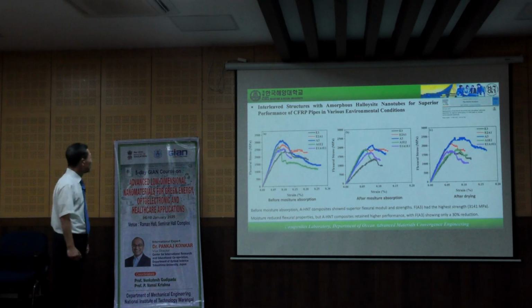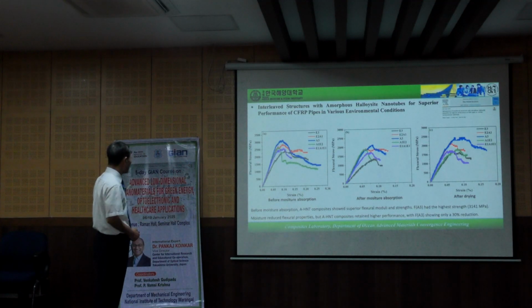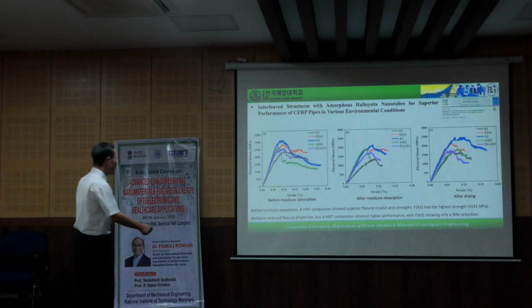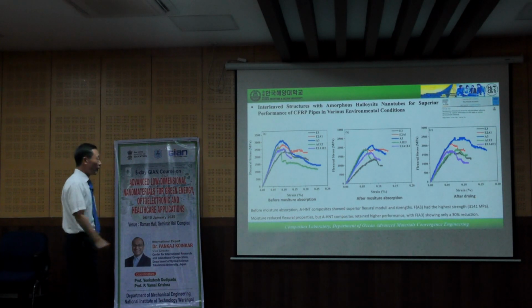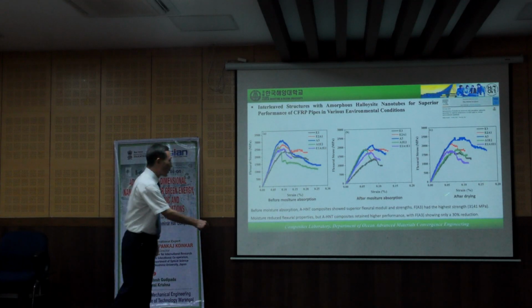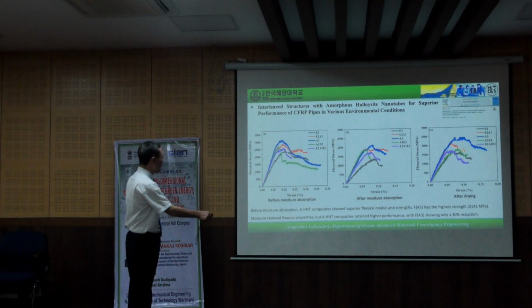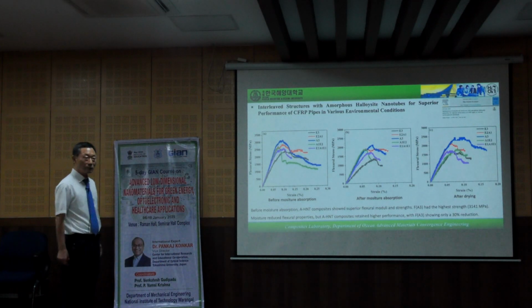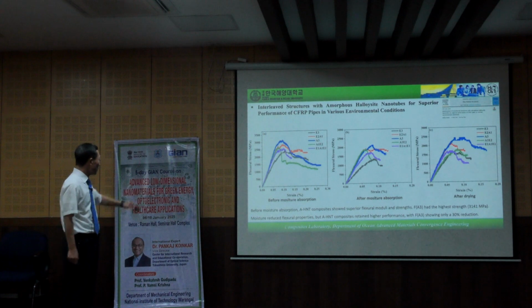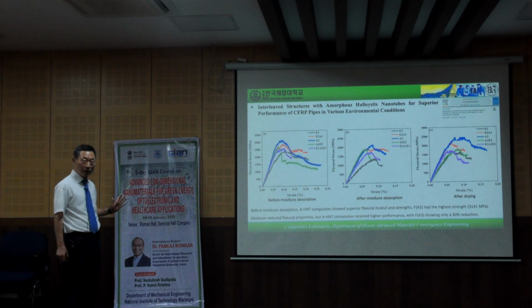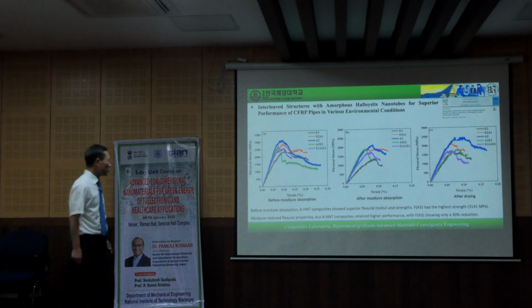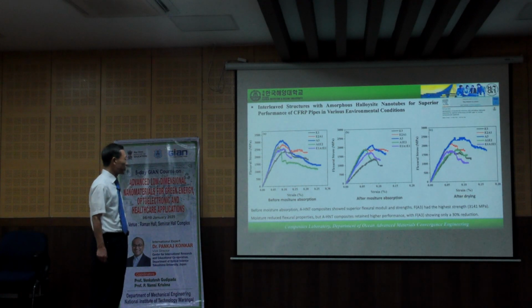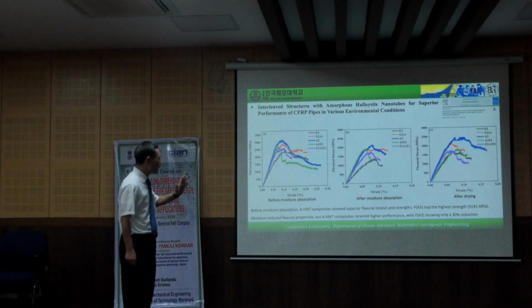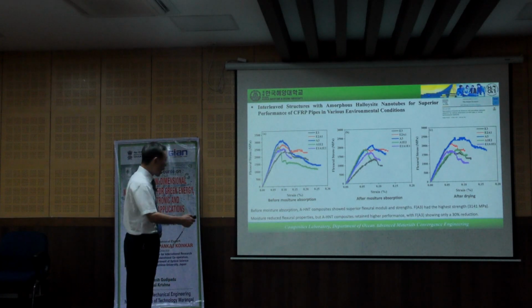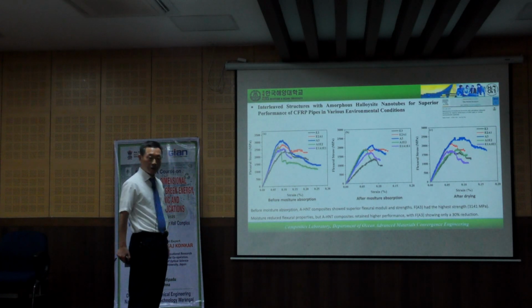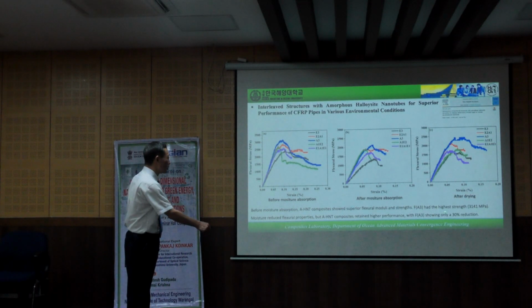Just to compare those results, flexural stress and strength: before moisture absorption, after moisture absorption, after drying. The situation is like this. We can summarize it like this. Before moisture absorption, AHNT composites showed superior flexural modulus and strength. A3 had the highest strength, meaning amorphous structure, 3 layer, showed the highest strength.